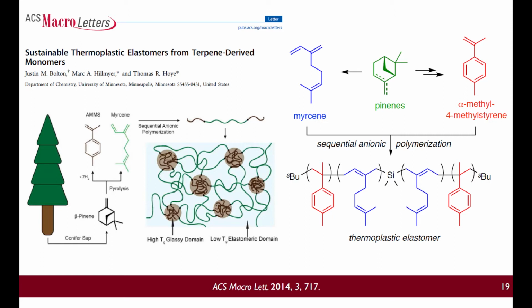Now, the nice thing about this is it behaves not unlike those materials I just showed you, but it turns out these two extra methyl groups on the styrene lend itself to having a higher glass transition temperature than polystyrene itself. So actually, this has much more thermal resistance than the typical Kraton materials that I showed you earlier. This is a way that sustainable polymers can actually enhance the property profiles of these types of materials.